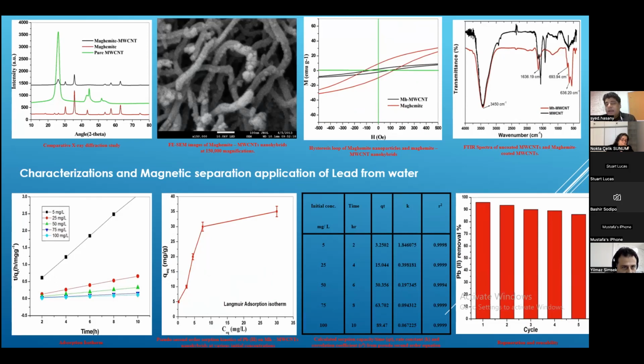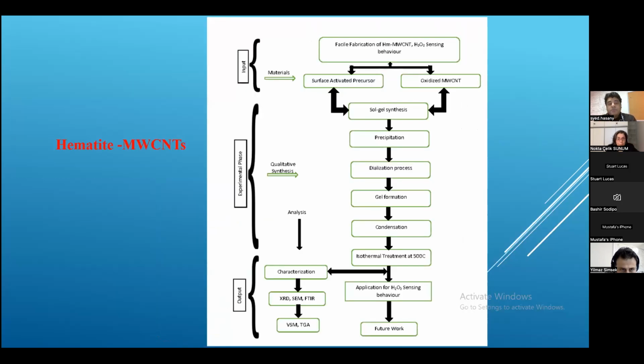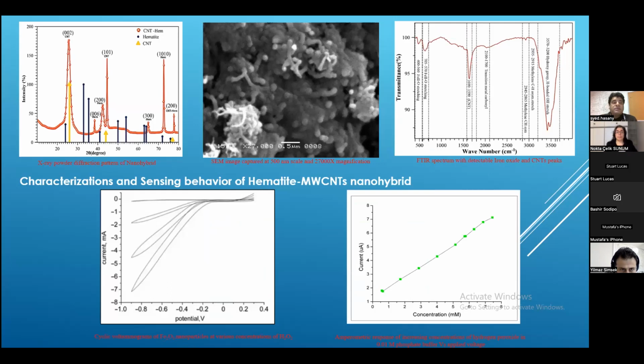In the maghemite phase, the peak at 32 theta is almost one third of the peak at 35 theta. But in the case of hematite, these peaks are very similar to each other. It's not a 1:3 ratio, it's like 1:2 or 1:1. So this is a major difference we can find by XRD.